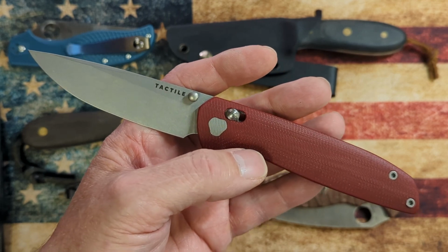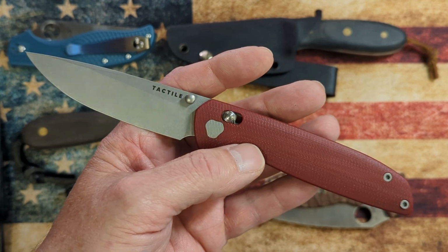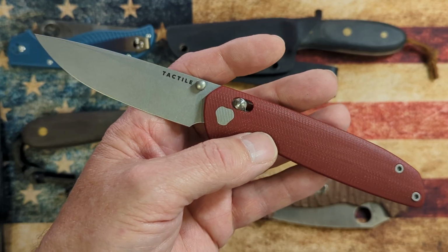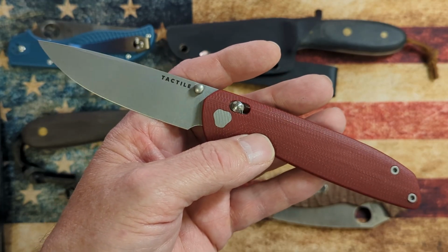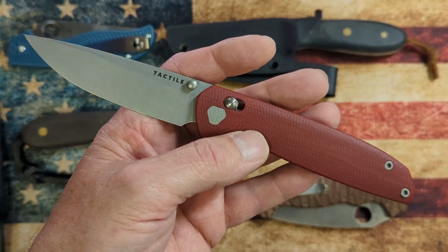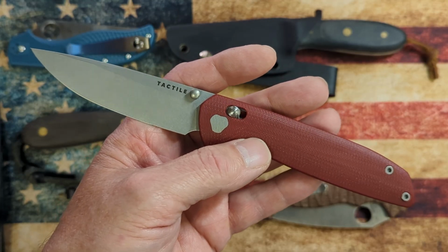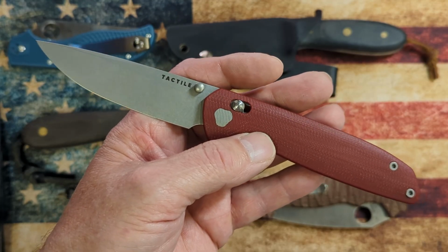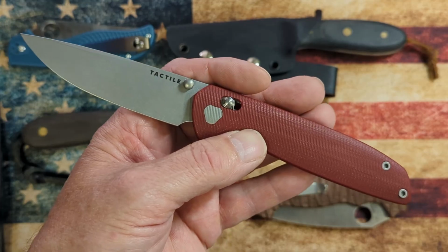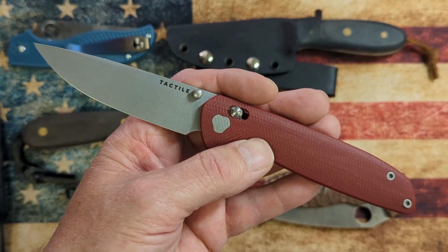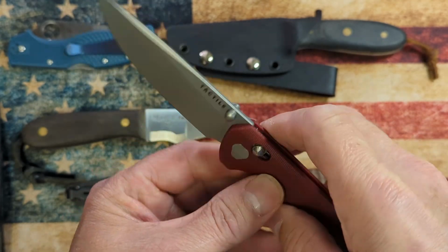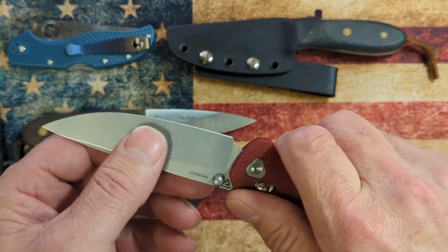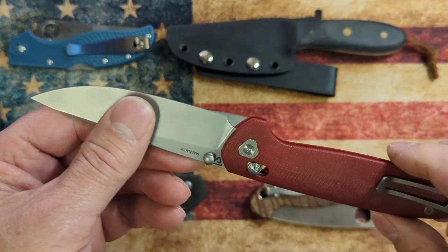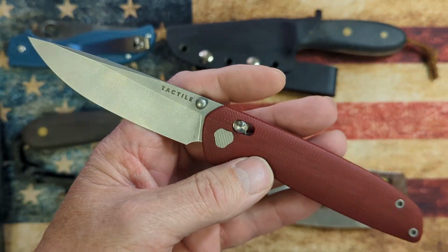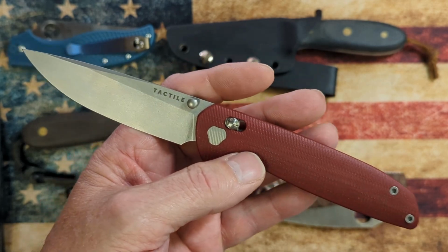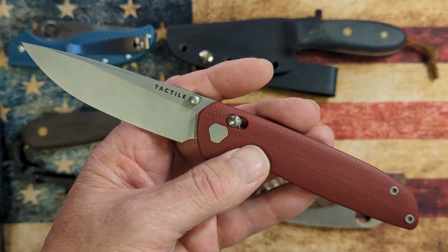You can take 1095 and run it at around 59 Rockwell, and you can do carving in wood and the edge will hold up okay. Now, if you want more toughness, you can lower that hardness down to around 56. You will have a knife that'll baton and is not going to break on you, but when you try and do some of that carving, especially if you get a little bit of twisting motion in there, you will roll that edge. So by increasing the toughness, the edge stability actually went down. So they're not necessarily linked together.